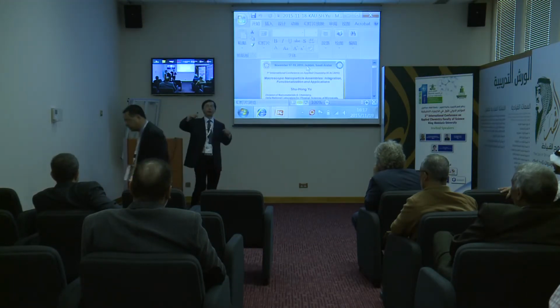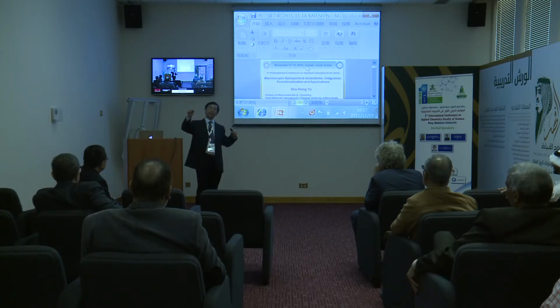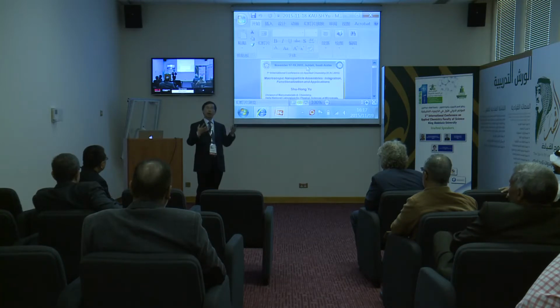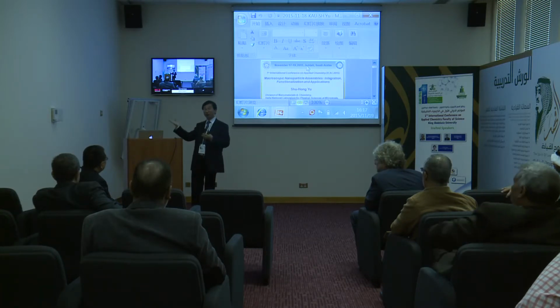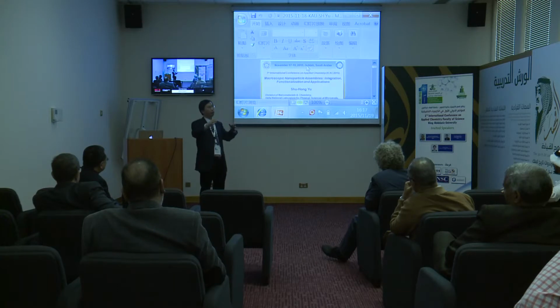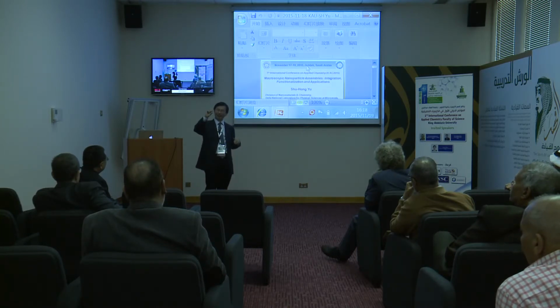Very good question. So that's the reason why we choose ultra-thin nanowires with high aspect ratio and tunable diameter. But the good thing is that we use this very tiny stuff. We want to introduce huge surface area, and we want our ultra-thin nanowire to become more reactive so that you can access different kinds of material. That's one issue. And another issue is that the one-dimensional structure is good for you to make assembled structures, compared with zero-dimensional dots or cubics or some other material. Because they have a huge surface area and also very thin thickness. So that's another consideration.